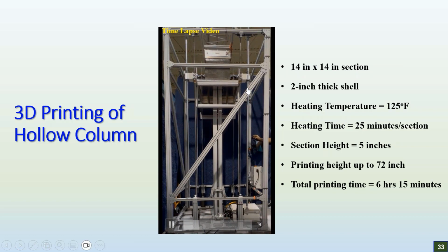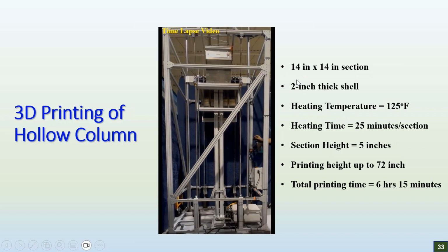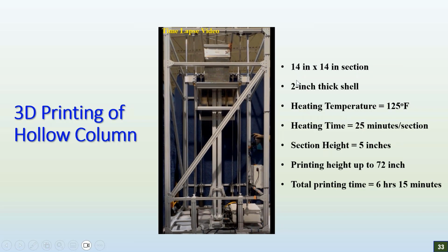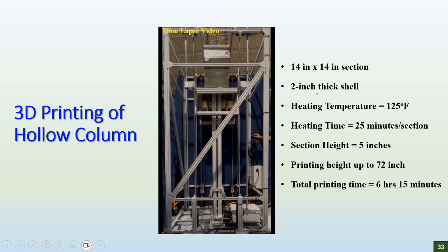So with this printer, we printed a 14-inch by 14-inch section of hollow column with a 2-inch wall thickness of the shell. Each section was 5 inches in height and was heated at a temperature of 125 Fahrenheit. And 25 minutes of heating time was given to each section before moving to print the next section. And with this particular printer, we could actually print a hollow column up to 72 inches.